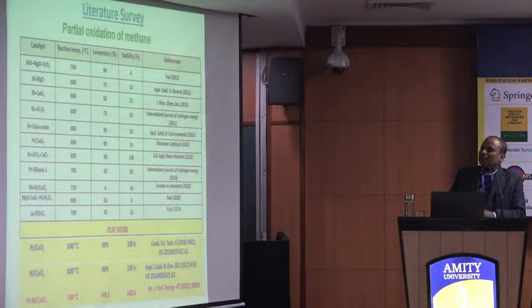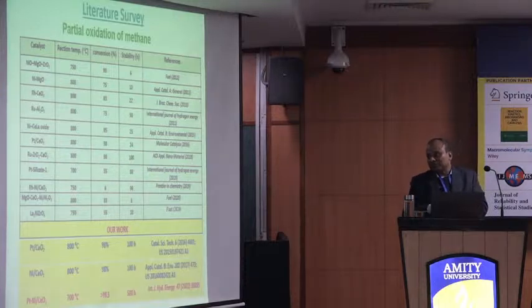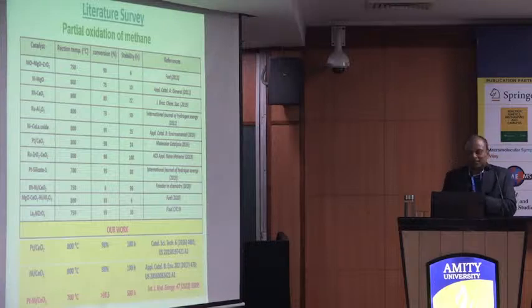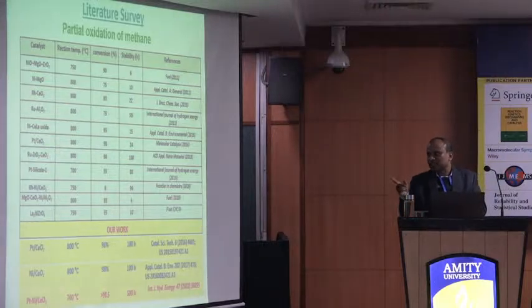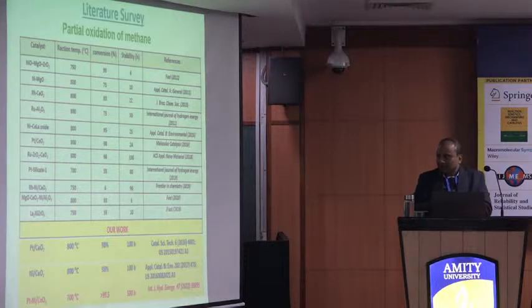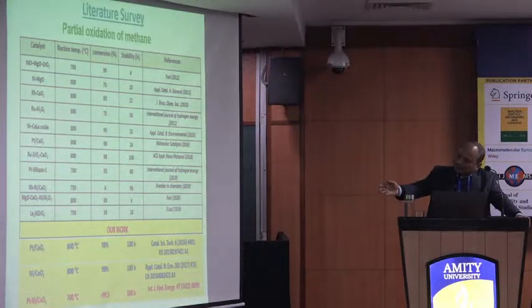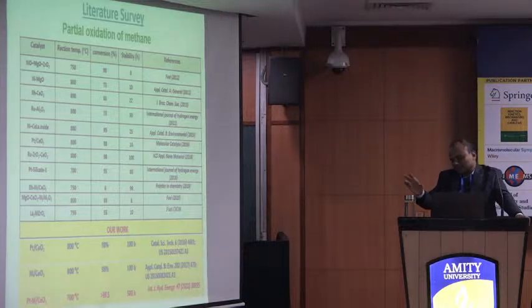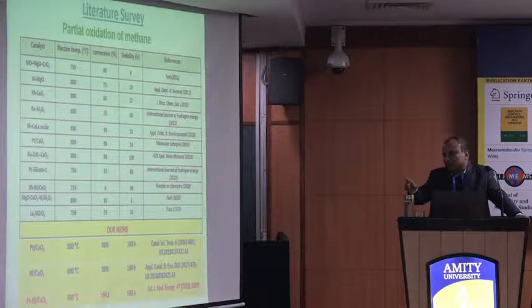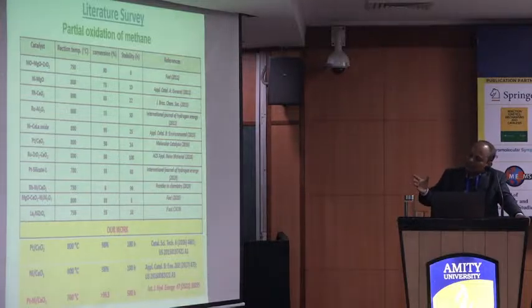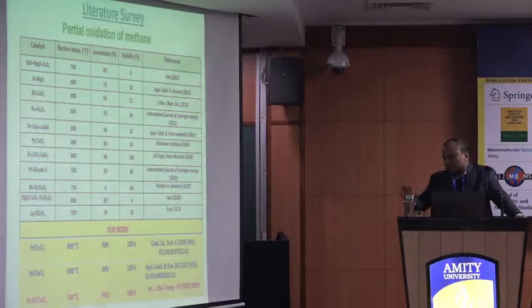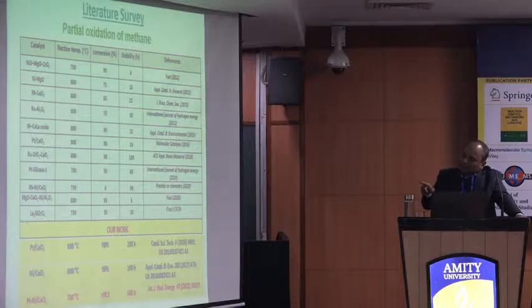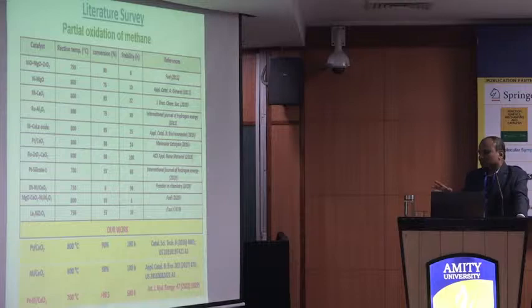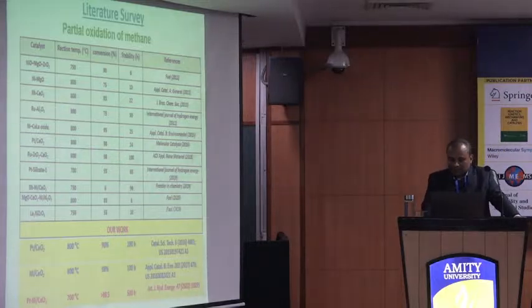For partial oxidation, there are lots of reports in the literature, but the main drawback is that either you need very high temperature or the conversion is low. At the same time, the major problem is the stability of the catalyst. In most cases, the catalyst is highly deactivated. For the last 10 years I have been working in this area and have several patents, including some publications. Initially, we saw that platinum on ceria is stable up to 100 hours. Then we developed a catalyst, nickel on ceria, which is also highly active, but after 100 hours it also deactivates. Today, I will talk mainly about the mixture of platinum and nickel supported on ceria, which is very active even after 500 hours at 700 degrees centigrade.